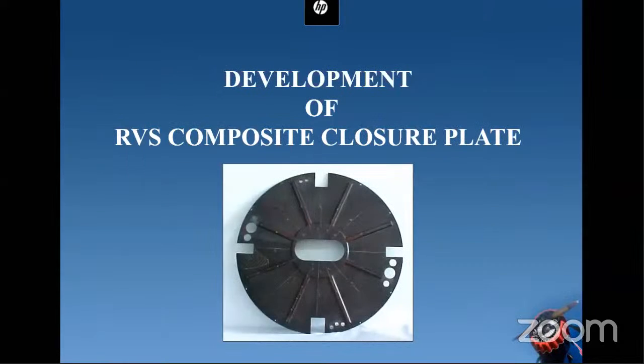Here there is another case study, a closure plate, the RVS composite closure plate, which is meant for re-entry vehicle structure. This is developed by composite press molding. It is made of carbon fiber and phenolic resin, as the plate has to withstand severe thermal load. That's why we have used phenolic resin, and ribs are also incorporated in order to avoid deflection of the component. This component is made in one go by using a two-sided mold in a compression molding technique, and for the sake of passing cables and other things, we have made small cutouts.